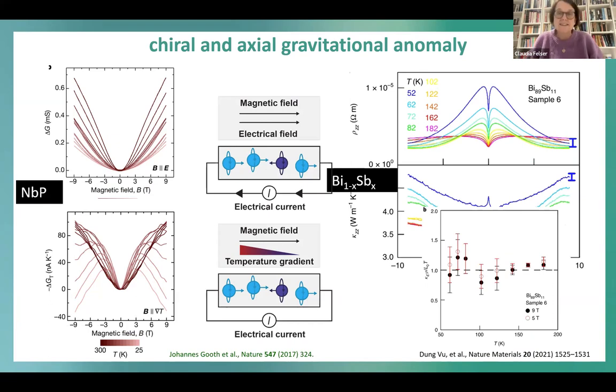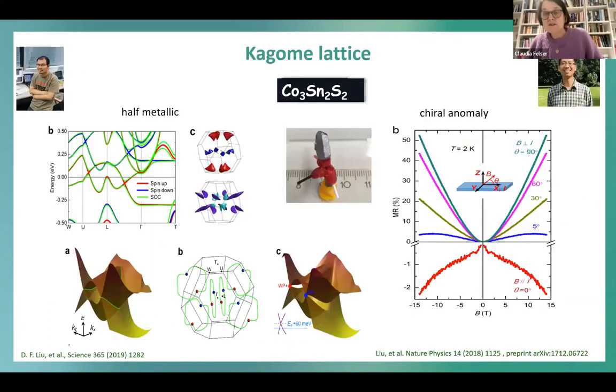But you see it also in a magnetic system, which is the next slide. We found a very nice kagome lattice, and everybody's excited about the kagome lattice. If you want to write a Nature paper, make a kagome lattice and send it to Nature. I think they are totally crazy about kagome lattices, so even if it only has one property, it doesn't matter. Here on the left side you see the band structure, and again nicely this crossing. Here you have again only the valence band and the conduction band crossing in this magnetic material, and you see the Weyl points, the red and blue dots here.